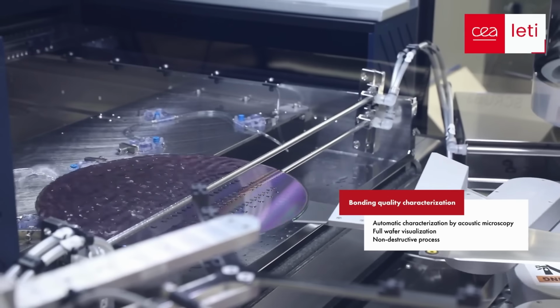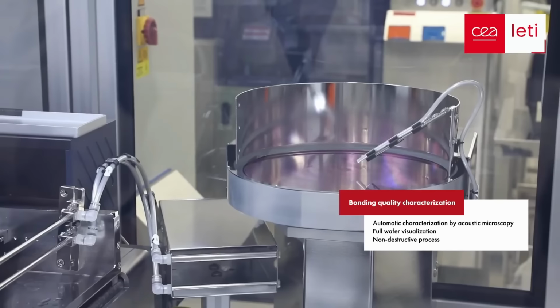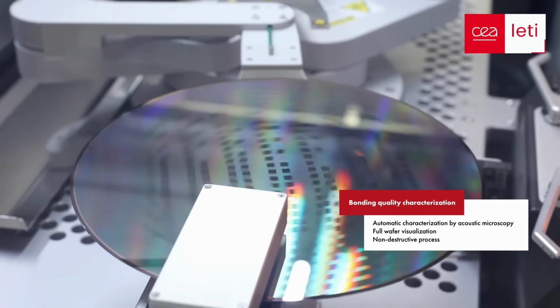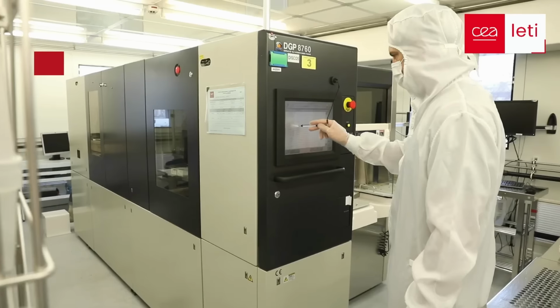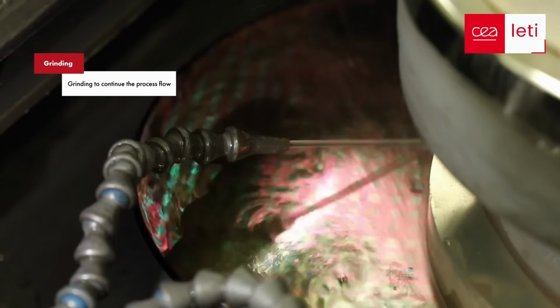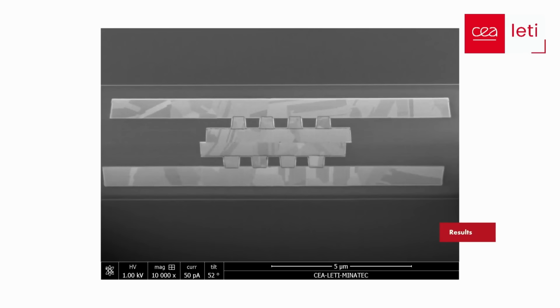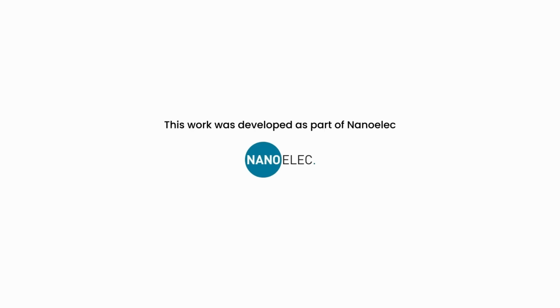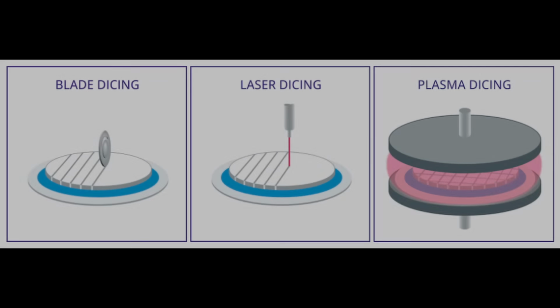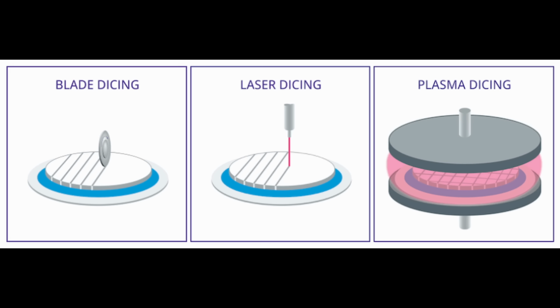Cutting the dies before bonding is also a problem because the wafer dicing process releases a lot of particles, which can contaminate the surfaces of the chips and negatively affect bonding. A single particle can block the bonding process for many interconnects. That's why chip-to-wafer bonding doesn't use blades or even lasers to cut the dies from the wafer, but plasma, because plasma cutters create the least amount of particles during the wafer dicing process.